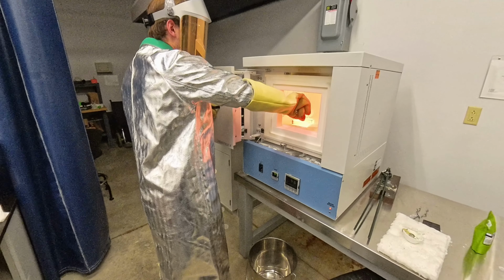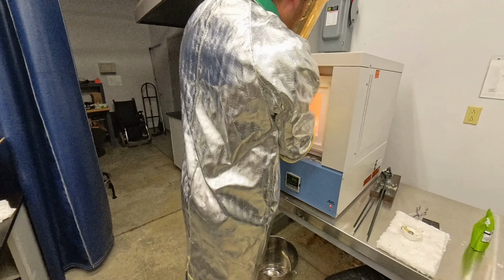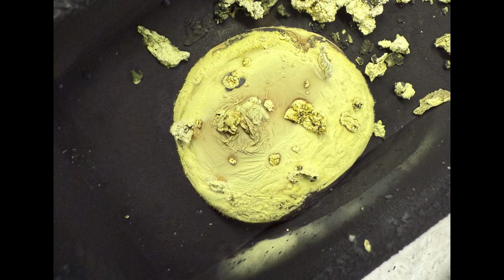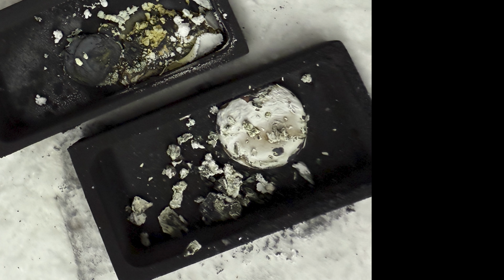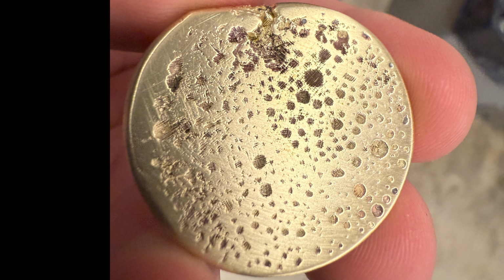I then was able to pour, and I actually got a pretty good glob. Sadly, some zinc did boil off and a good amount of oxides were formed, as you can see by the horrible evil yellow. But I got a pretty interesting result. This image was taken after sanding and polishing, but this was not etched. I was able to get these dendritic growths during solidification. And you could see these patterns before polishing, but it certainly made it prettier and much more satisfying.